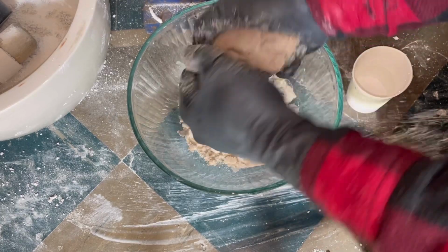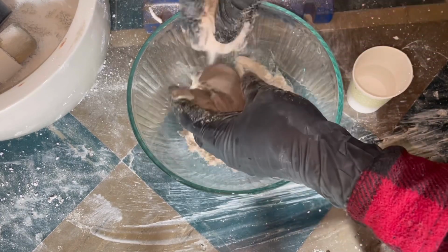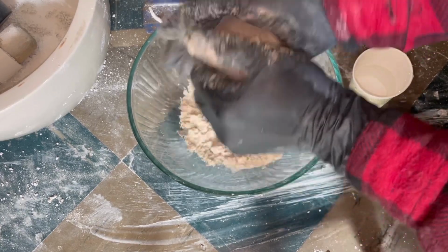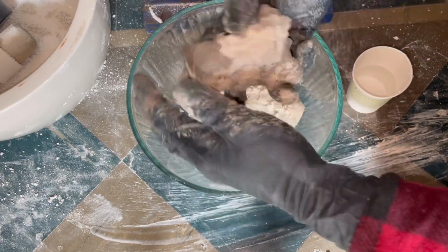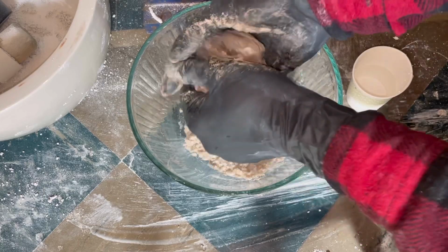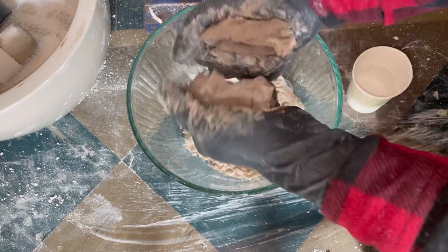Also, the sand provides channels for gases to escape during firing, so it's more resistant to moisture. The sand does make the crucible less strong against the flux, though, because the sand is easily dissolved by the flux. So the more sand you add, the less likely the crucible is to withstand being used. But since I tend to use my crucibles only once, you can go with quite a lot of sand here. 50% or perhaps even a little more.